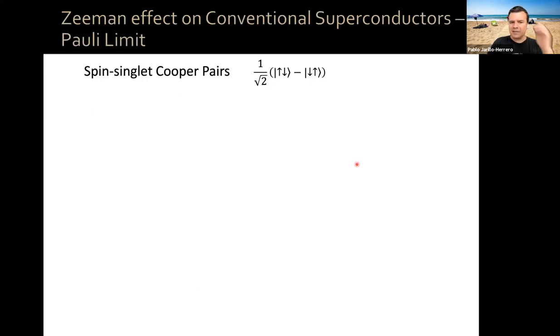Now, as a reminder, in conventional spin singlet BCS superconductors, the Cooper pairs are spin singlets, up-down minus down-up. The binding energy is given by the superconducting gap, which happens to be 1.76 kB times your critical temperature.